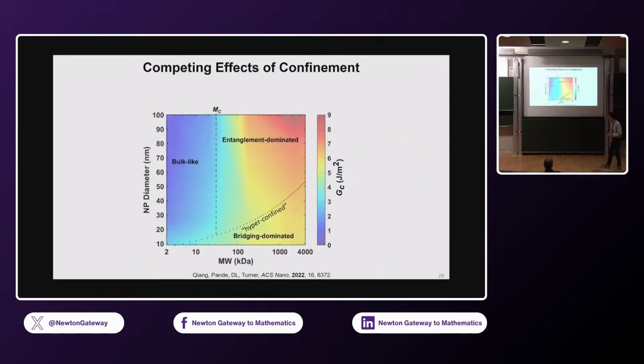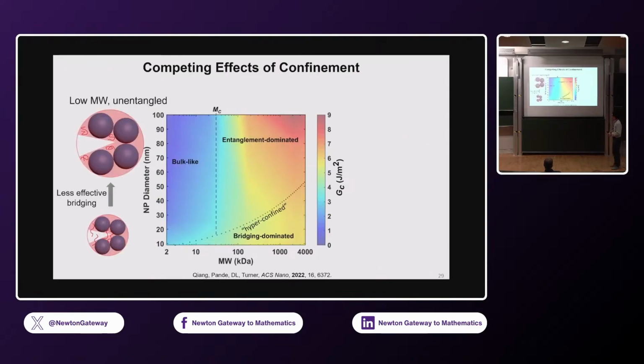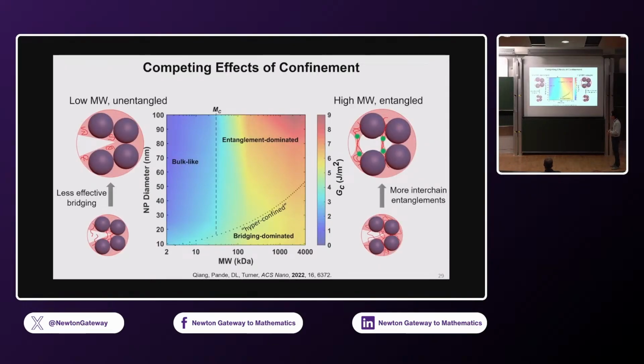So here's the picture that we have, okay? When you have particles that are very small, that means the pores are very, very small, right? So in such a scenario, the polymer has to be stretched, okay? They have to be very stretched. So in this case, what would likely lead to toughening is when the polymer gets longer and longer, it bridges multiple particles, okay? And this bridging now induces toughening of the composite material.